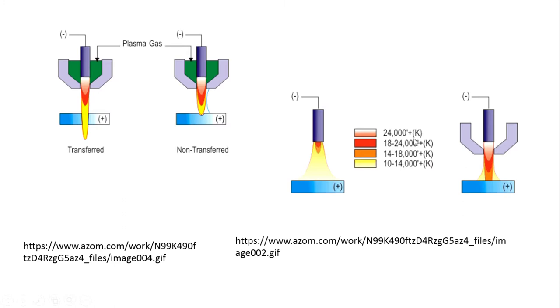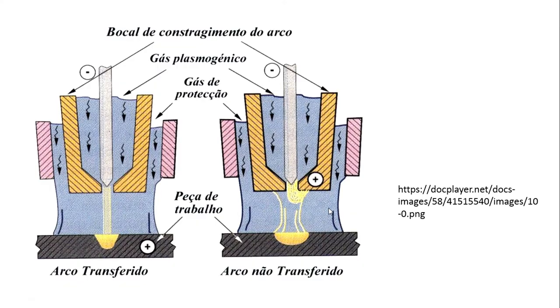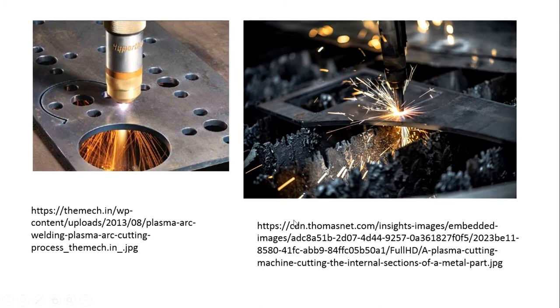The temperature range goes from 10,000 K up to 24,000 K. The negative terminal is connected to the electrode and the positive to the workpiece, so you can see deeper penetration with less width. In non-transferred mode, the electrode is short-circuited to the nozzle, so part of the ions are absorbed there and only a few reach the workpiece, creating a wider bead with lesser penetration. The width-to-depth ratio changes between the two modes.